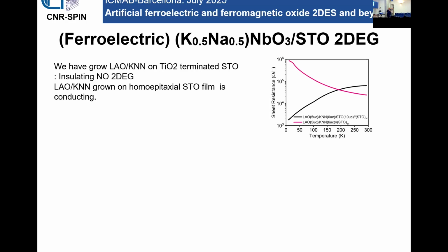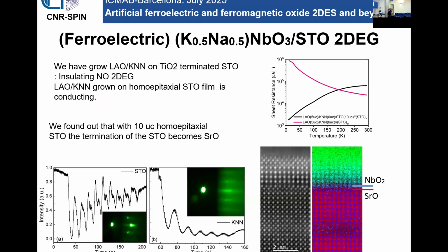It's quite complicated. So first of all, we tried, of course, to grow LAO on top of KNN on TiO2 terminated STO, because TiO2 terminated STO you can buy directly, so it's very easy to get TiO2 termination. But the gas is insulating. There is no formation of a 2-dimensional electron gas in that case. If we, on the other hand, grow an epitaxial strontium titanate between the single crystal TiO2 terminated STO and the KNN, we can get a 2-dimensional electron gas.